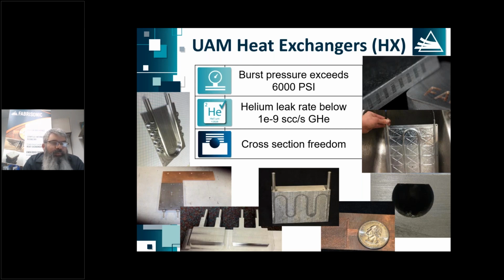So the top right is what we call a harmonica. Those channels are about 150 thou wide by about 6 thou tall. So that's a very dense flow path. But in that particular part, about an inch away, that turned into a header that opened up into a larger flow channel. So throughout the part, we can change the contour of the inside shape of those flow paths, which gives the designers a wide berth, a large ability to make very, very intricate designs for thermal performance. So those are some high level examples.